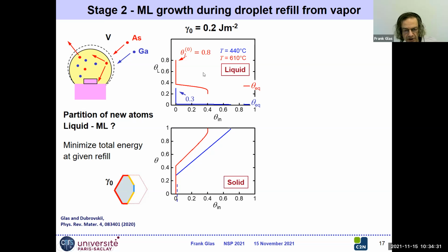If I'm at higher temperature, then things may be different. So I deplete, but I don't deplete to the value at bulk equilibrium. And then you see that the concentration in the liquid keeps decreasing. So it does not stay at equilibrium with the bulk solid. It is something which decreases, and it decreases very fast at the end, below the equilibrium with the solid, which is another instance of the phenomenon we have seen before. So here we have something which is more complicated. But this is related to the fairly large energy of the monolayer.